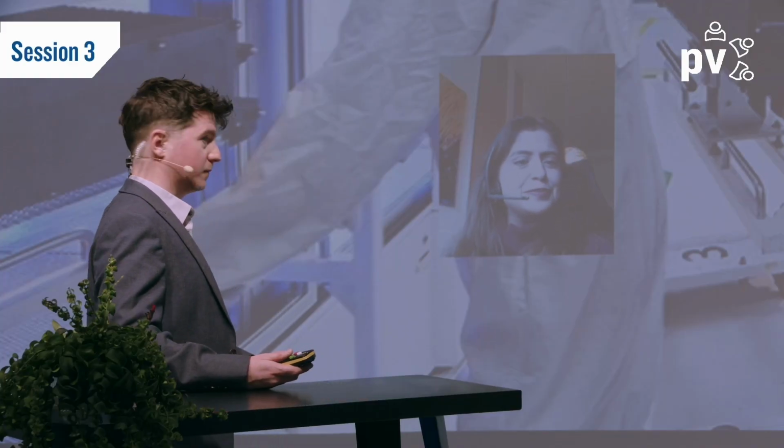So we have passivating contacts with metal electrodes for the silicon surface that can still reduce recombination. We have some material innovations, so we can use certain films to enhance anti-reflection. At the silicon cell level, we have optical improvements, so there is a lot of discussion about photonic crystals and refractive index improvement. We still have room to go there, but I think in the upcoming years, metallization will be key. There are a lot of discussions about new materials emerging to reduce costs, but also to improve long-term reliability. So I think we have a lot of internal features from the module to give us room for TOPCon, at least for the next 4 years.